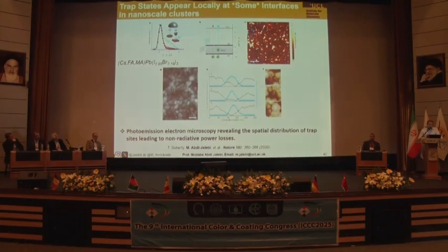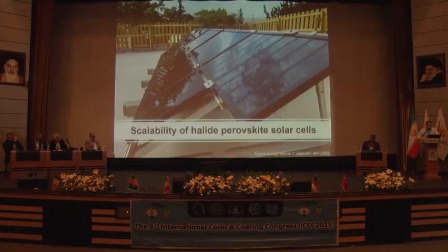And what we have done in this work is we look at the AFM techniques and combine them with the PEEM, and then we locate the defects, and we found that they are mostly located at the grain boundaries. As you can see, this is the grain structure. You can see a lot of grains over here, and these blue spots are the defects.